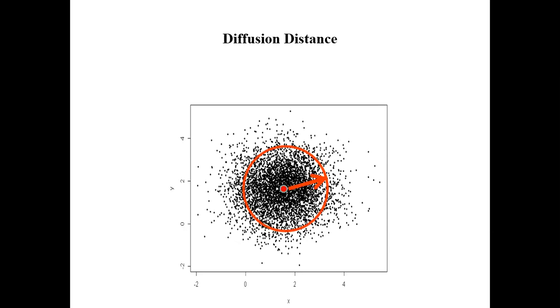Okay, so this typically means that if I start from the middle of the box and allow the particle to diffuse around over a certain period of time, t, I have the probability of finding this particular particle at a certain position. Now, this is what we use to describe diffusion. Instead of describing the exact location as we did for Newtonian dynamics, we use this stochastic way to describe the diffusion. And in this sense, it's reasonable to introduce an average distance traveled by this diffusive particle over time t.